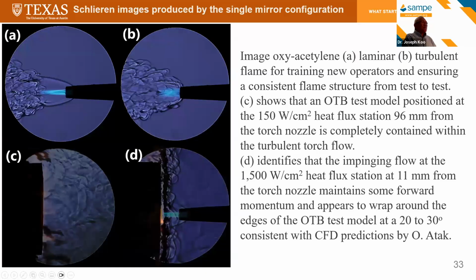Okay, this is something that one of my PhD students did in understanding the imaging using schlieren, A, B, C, and D. A is where we are looking at laminar flow. B, where we trigger the turbulent flow. And C is what we are measuring using OTB, using a very low heat flux, 150 watt per cm square. And D is when we push to very high heat fluxes. You can see the flow field is very different when you have the OTB impinge on the ablative material. We are also linking with some of the CFD models developed in our group, and these data will help us validate our OTB CFD model.